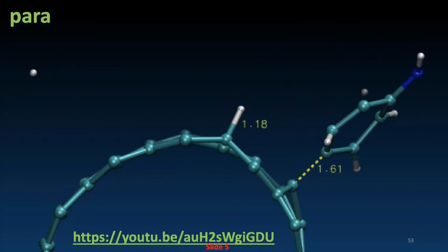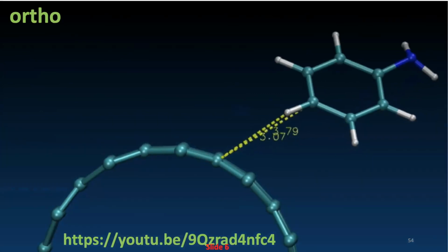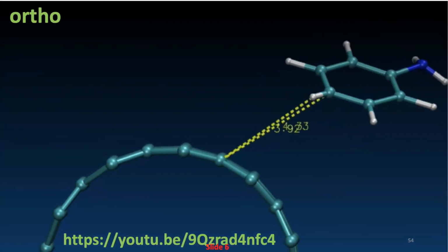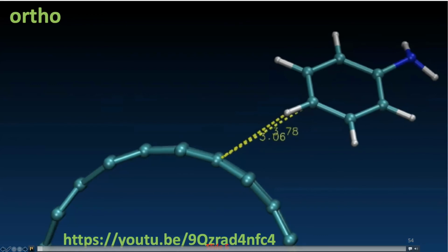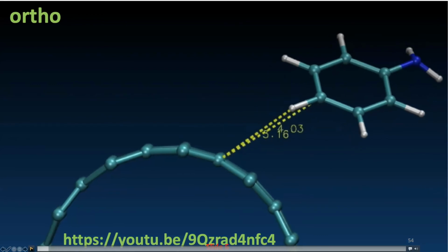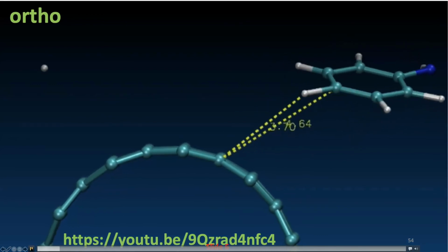You see that photoexcitation disturbs the system from equilibrium, and there is first a transfer of the hydrogen from this aniline to the surface, and then carbon-carbon bonds form, and it is one type of defect. And by slightly changing parameters of the photo-induced simulation, one can get another pathway.